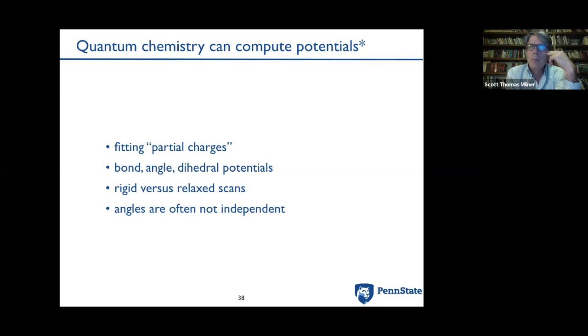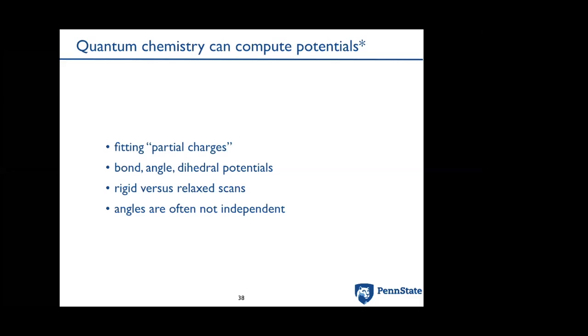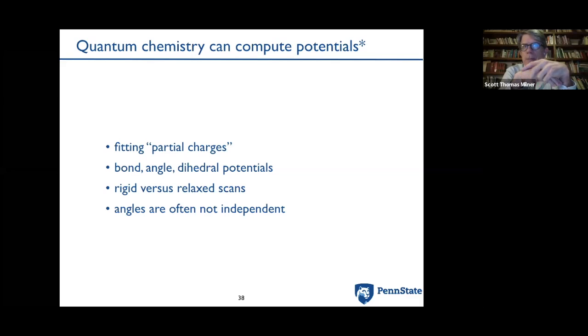Also, bond and angle and dihedral potentials. So every pair of atoms that are bonded, two carbons in a hydrocarbon chain, have a quite stiff spring between them with a very well-defined rest length and a big stiff spring constant, and it's a rather harmonic interaction for the small kinds of deviations that you're going to have in ordinary temperature situations.